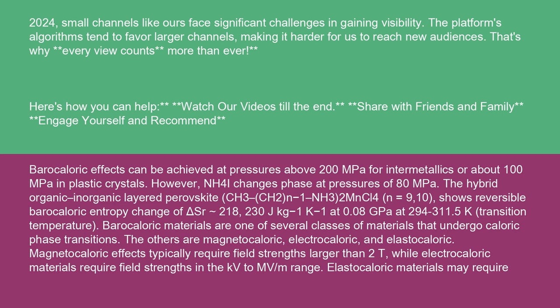Barocaloric effects can be achieved at pressures above 200 MPa for intermetallics, or about 100 MPa in plastic crystals. However, NH4I changes phase at pressures of 80 MPa.